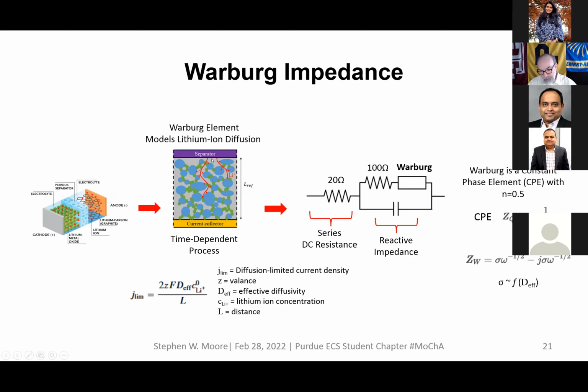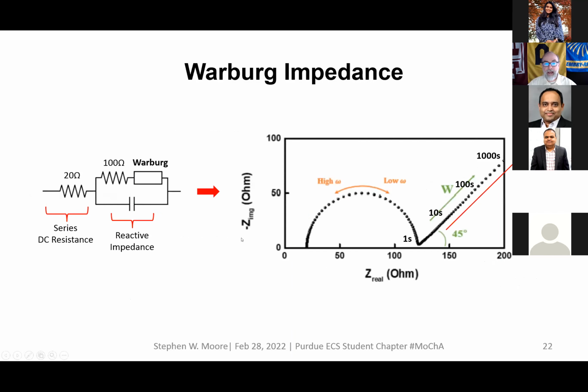Now, this time-dependent process is really interesting because the more lithium ions I try to cram into the electrode, it gets proportionally more difficult to cram the next one in. And therefore, when graphed on a Nyquist plot, it has this tail that goes off to infinity, infinity time right there. And so given my model here, and I have a 20 ohm resistor and a 100 ohm resistor, now I add a Warburg impedance on, and here's my semicircle. But once I hit the bottom of the semicircle, the Warburg impedance takes over.